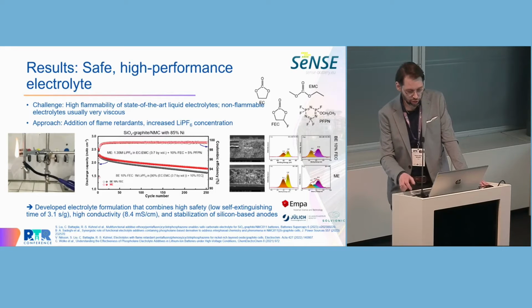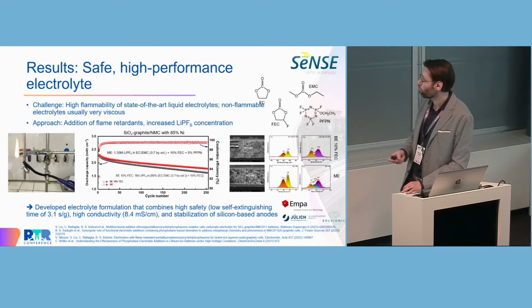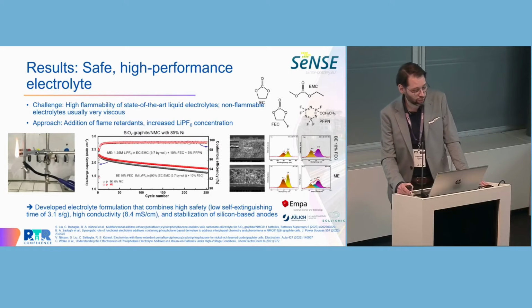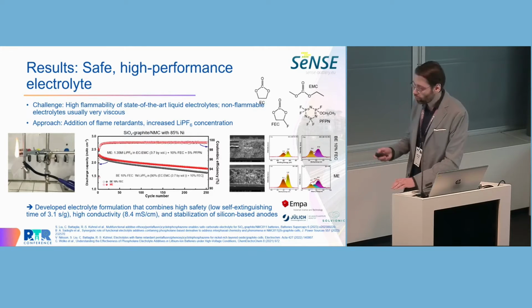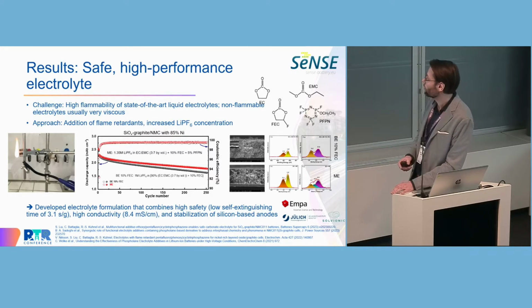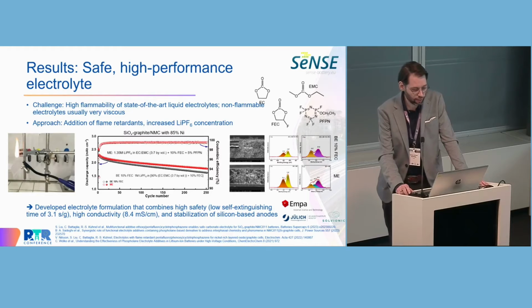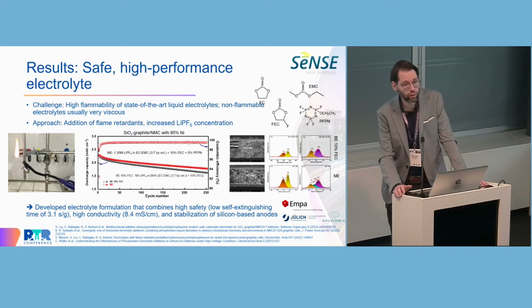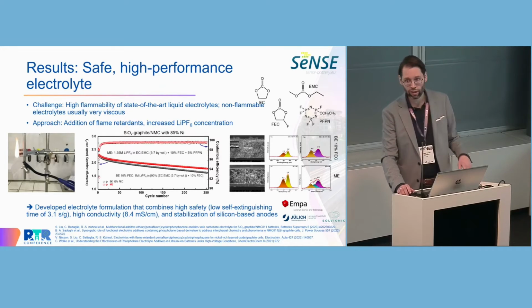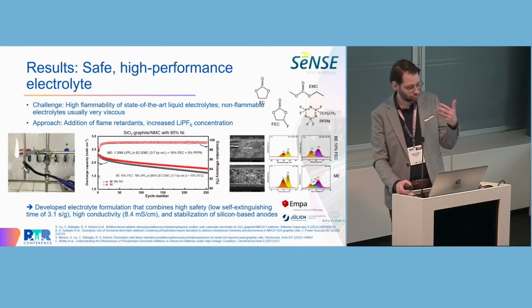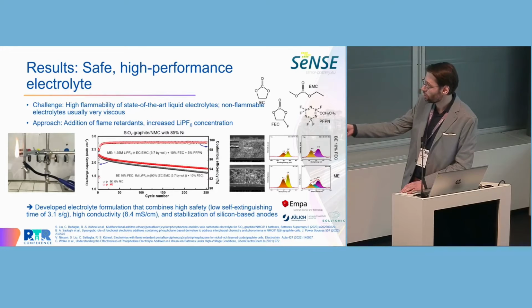So our approach was to stick to the classical carbonate solvents and to just add some flame retardants to the electrolyte, and we focused on this class of cyclotriphosphazene type flame retardants. And when combining 5% of this flame retardant with a slightly increased LiPF6 concentration of 1.35 molar compared to the more typical 1 molar concentration, we were able to render the electrolyte non-flammable in terms of its self-extinguishing time, which is the time it takes for the electrolyte to stop burning after you put it on fire, for example, with such a lighter.